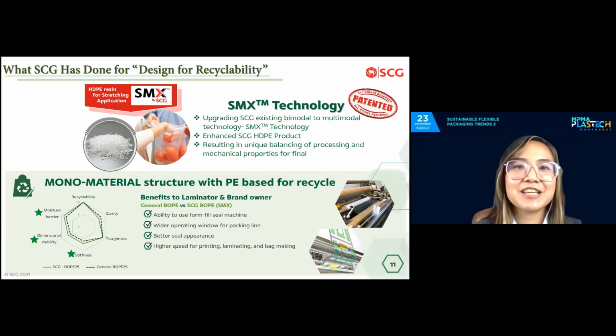In fact, at SCG, we are not the first one trying to use PE in monomaterials packaging. The general BOPE has been used commercially in the market for a few years. However, because of their too low dimension stability, the laminator needs to reduce the production line and also the production rate, which tends to bad seal appearance, and it can lead to a narrow operating window of the packaging speed. So with this problem, this is why SCG BOPE developed from the SMX technology can solve this problem.